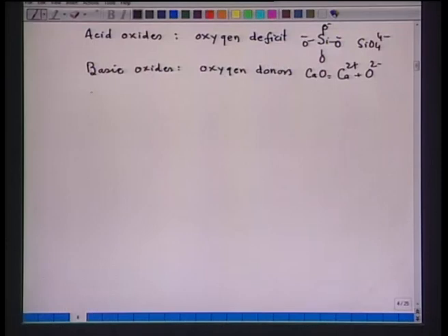when we break all four vertices of the tetrahedra. Then the size of the ion will be smaller, the energy required for flow will be smaller, and the fluidity of the slag will be very high. So, considering that the most important oxides in steel making are SiO2 and Al2O3, Al2O3 also behaves in a similar way.